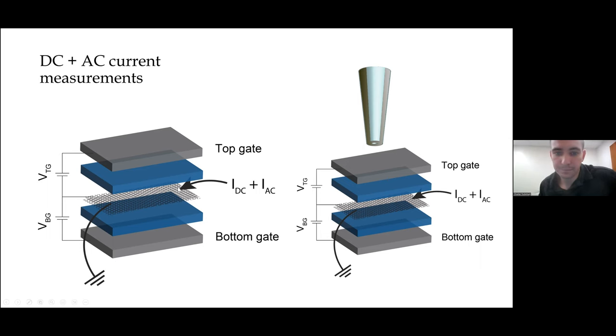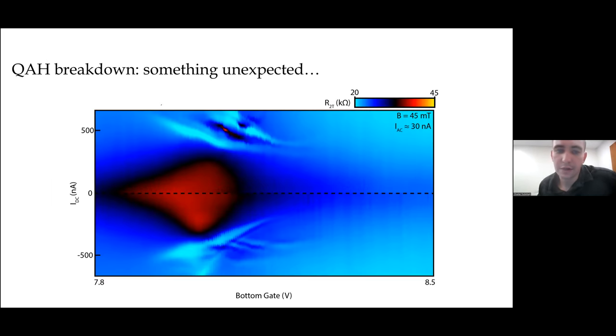So this is the transport data through the quantum anomalous Hall plateau as a function of bottom gate. On the y-axis, I'm showing you DC current. We're applying a DC plus small AC current. And a lot of this is pretty much expected. As you increase current, you see degradation of the two-terminal resistance. Currents are entering the bulk, which reduces the total resistance of the system. There are a couple of things that are interesting. And I think the main one is that there's this sharp feature at finite critical current where we see something changing suddenly as a function of DC current. So the question is, is there a way for us to study what's going on here with the SQUID?